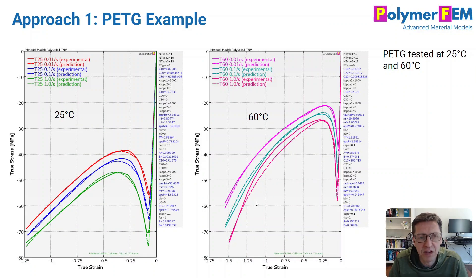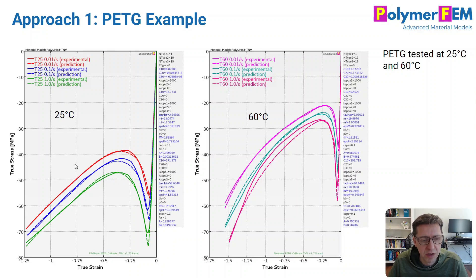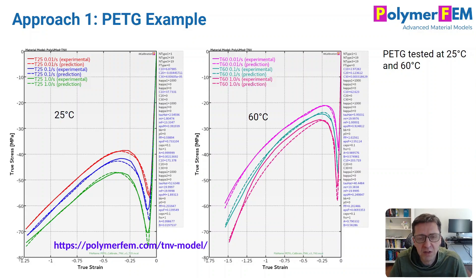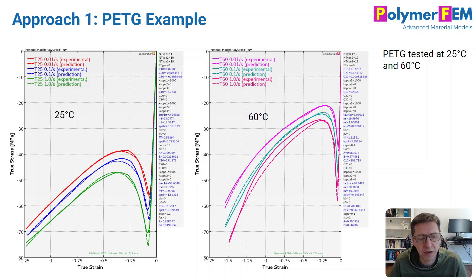But if you have a more advanced material, here's an example I'll talk about in this video. This is a thermoplastic called PETG, and I have uniaxial compression data for this material at 25°C and 60°C. The solid lines here are the experimental data. I calibrated a PolyUmod TNV material model — one of the models that is really accurate for all kinds of thermoplastics — and I get a pretty good fit to the data at each temperature.